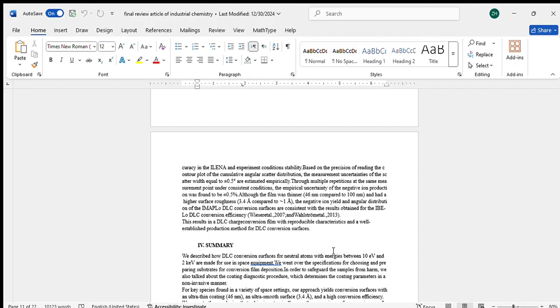In the optimization, the DLC layer was optimized to a thickness of 46.7 nanometers with a surface roughness of 3.4 angstrom, resulting in more reproducible and consistent conversion surfaces. The improvements were made possible by refining the coating process, including cleaning the substrate carefully and maintaining a clean environment during the deposition and testing.